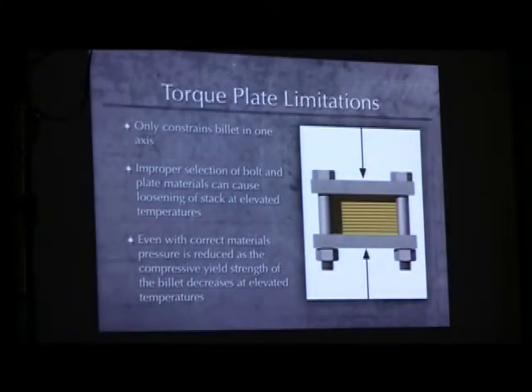So we had some limitations. The torque plates, did some research on things that we might improve it. One thing, if you choose your materials wrong, say you use stainless steel bolts, they expand at a greater rate than the metals in the stack. So instead of holding everything nice and tight when you heat it up, it all gets loose. Learned that one the hard way.